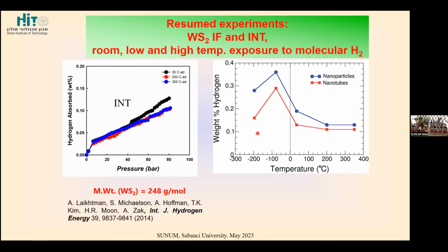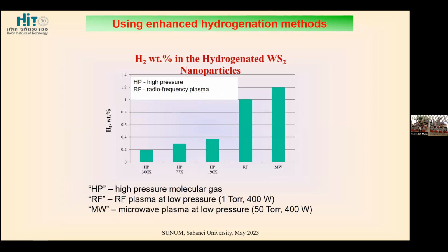When we lowered the temperatures to either liquid nitrogen temperature or dry ice temperatures, then we achieved much better results, and not for the lowest temperature, but some intermediate one. I will concentrate on this point later, because we have some competition between adsorption and diffusion. But again, this type of experiment did not provide us the best result that we are expecting. So here I will jump to other methods. We applied hydrogen enhancement by plasma, radio frequency plasma and microwave plasma, and then we jumped to more than 1 weight percent. I will talk about this result, which is quite a nice result for this type of material. So plasma really enhanced the results of this hydrogenation.